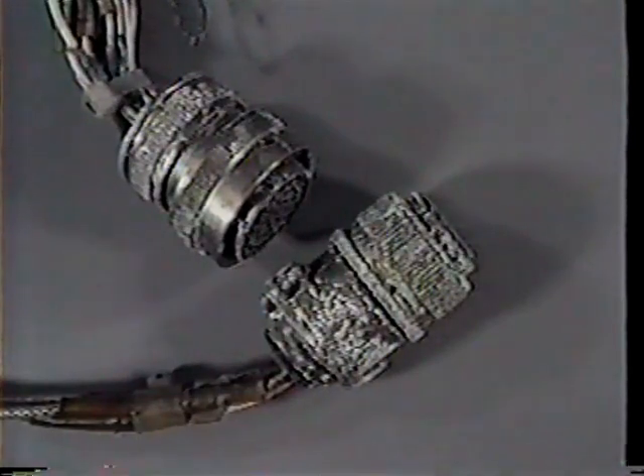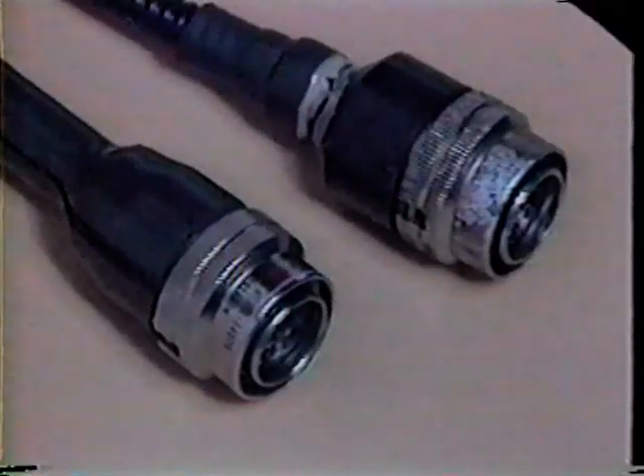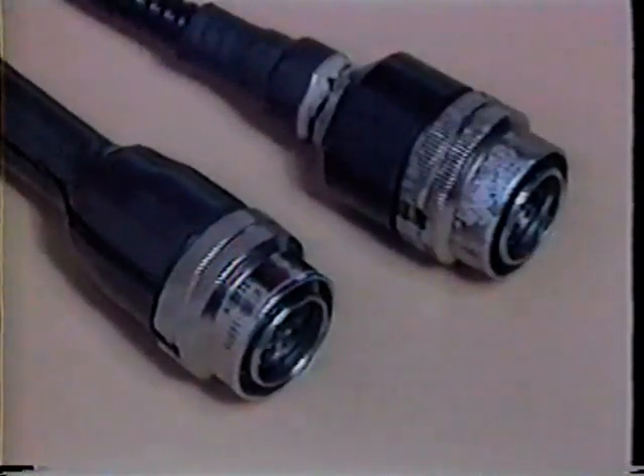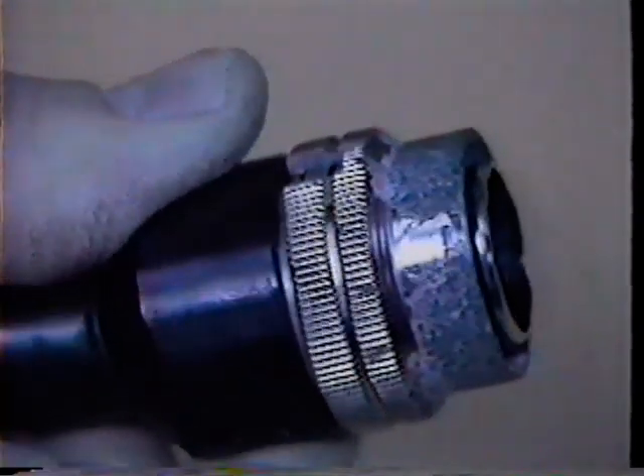Electrical connectors are also prone to corrosion, especially the de-icing kit connectors located on the rotor head. These connectors are made of aluminum and coated with nickel to reduce corrosion. When the plating on the back shell is nicked or scratched, the aluminum is exposed and may corrode. Erosion caused by blowing debris can damage the plating and expose the aluminum. This exposure enables corrosion to take place when corrosive agents and moisture are present. This eventually leads to the failure of the connector.